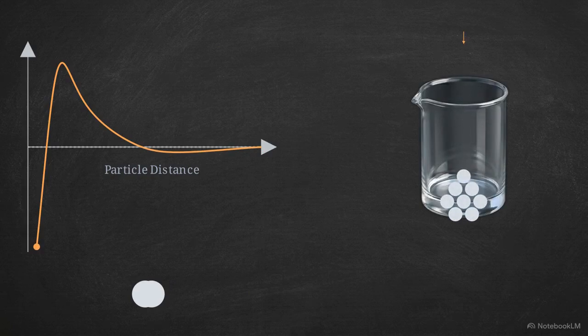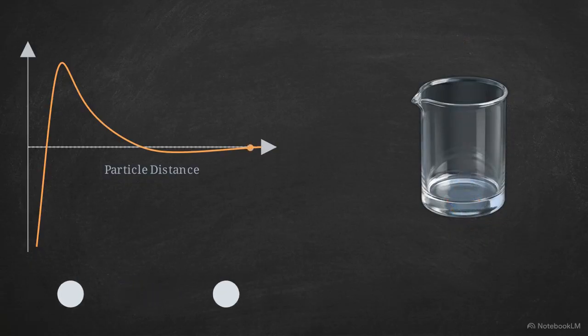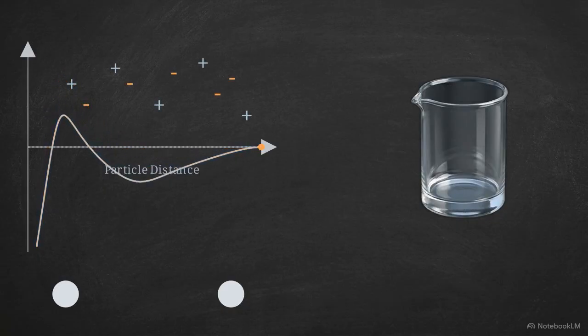In a suspension, gravitational forces pack settling particles tightly together at the bottom of a container. Once they enter this primary minimum, physical bridging and crystal growth lock them into a hard, irreversible cake that cannot be shaken apart. To prevent caking, we induce controlled flocculation.